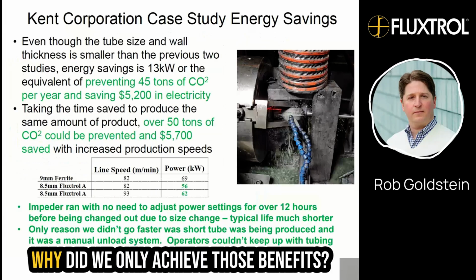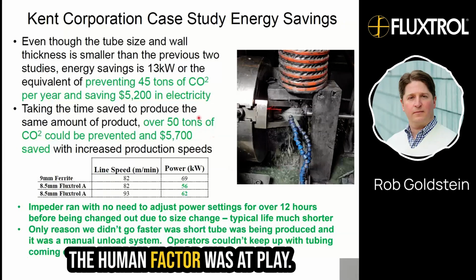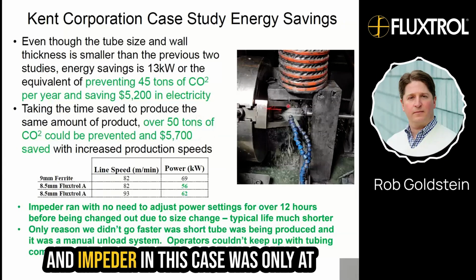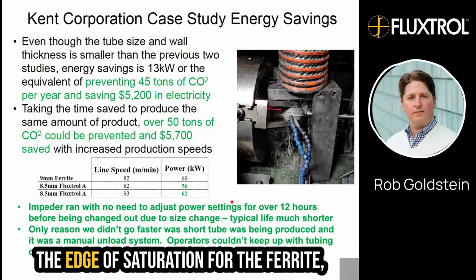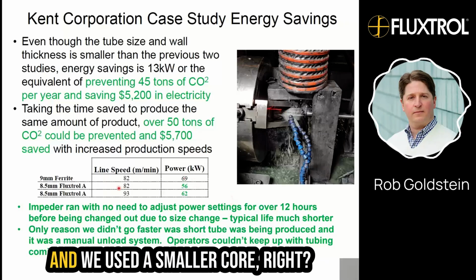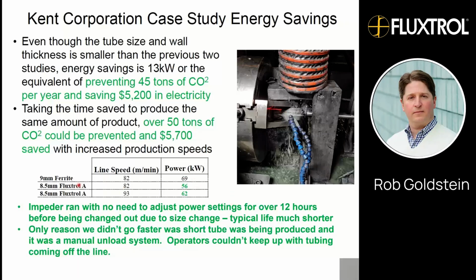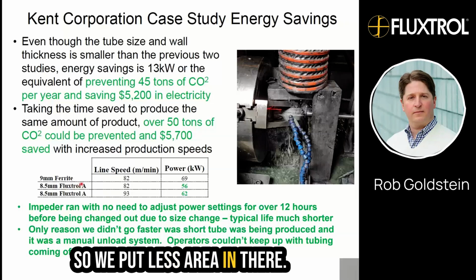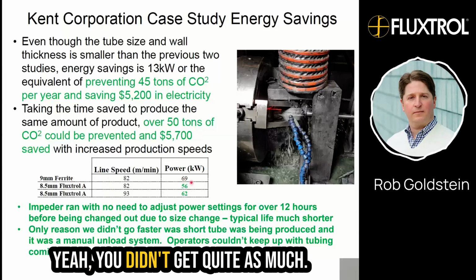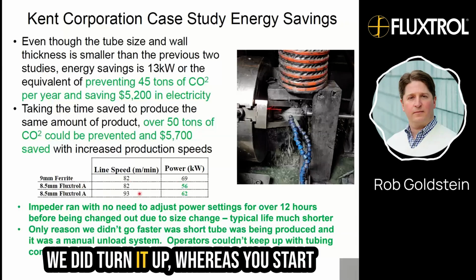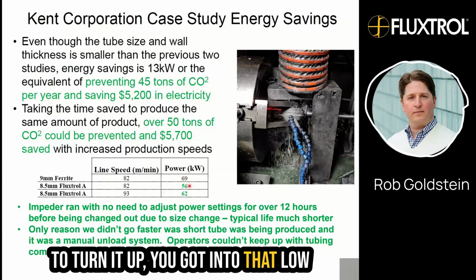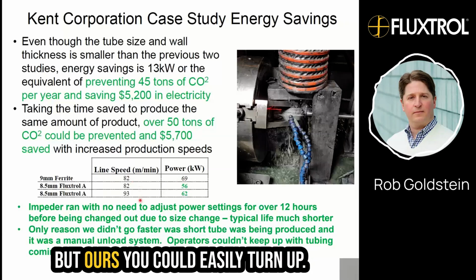You say, it's smaller, why did we only achieve those benefits? The human factor was at play. The impeder in this case was only at the edge of saturation for the ferrite, and we used a smaller core, right? So we put less area in there. Yeah, you didn't get quite as much. We did turn it up, where if you start to turn it up, you get into that low efficiency zone if you use the ferrite, but ours you could easily turn up.